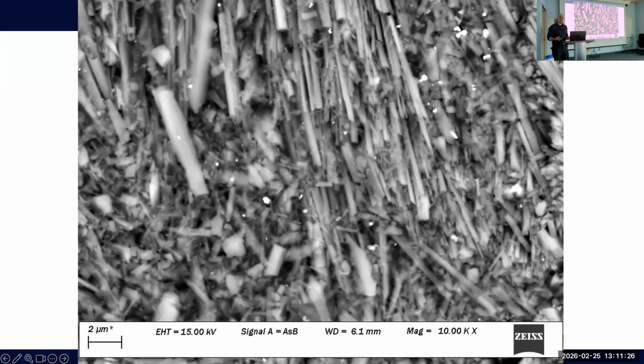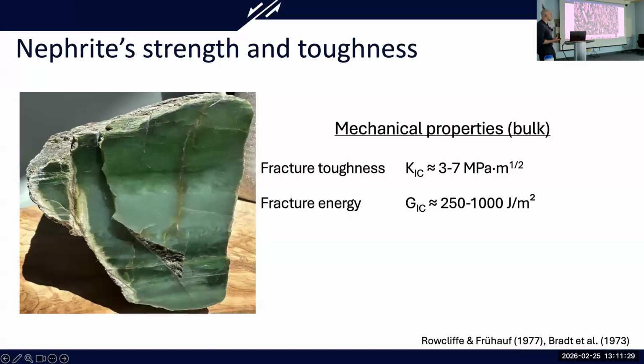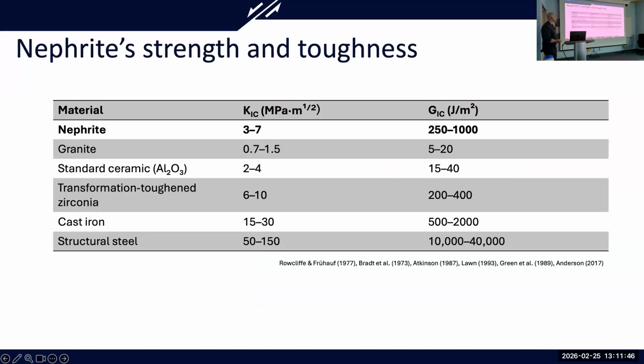And in fact, it's this fibrous nature that makes it so incredibly strong. So when we look at the mechanical properties, fracture toughness is significantly higher than any single mineral grain, and the fracture energy is incredibly high. Now, by itself, these numbers might not mean a lot to you, but if we compare them to some common earth materials or some common engineered materials, for example, a granite, we're looking at 1 to almost 2 orders of magnitude greater fracture energy for the nephrite. The nephrite's stronger than standard alumina ceramics. It starts to be comparable to a very modern transformation toughened zirconia.